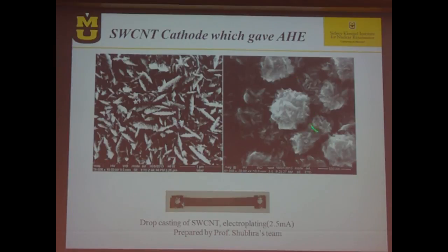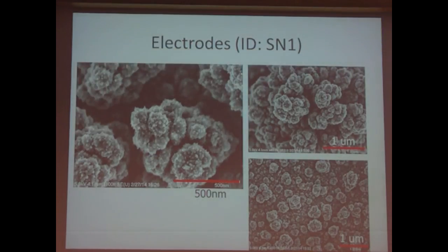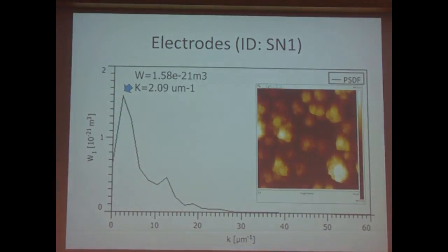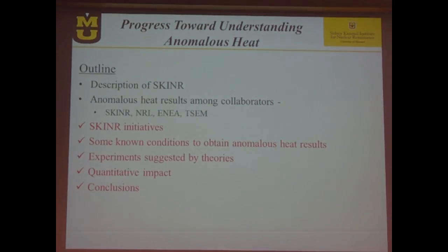This is how the surface looks. Actually, this is the palladium upper layer. Remember, we are talking about a sandwich. And this is the cathode. And at different scales, you see a cauliflower. It's like fractals of cauliflowers. And when we analyzed the surface morphology with atomic force microscopy and Fourier analysis, we see again the two peaks, and that increased the probability to get excess heat.